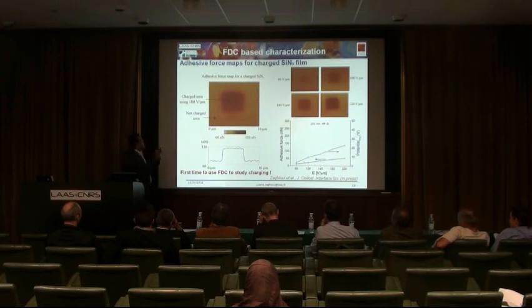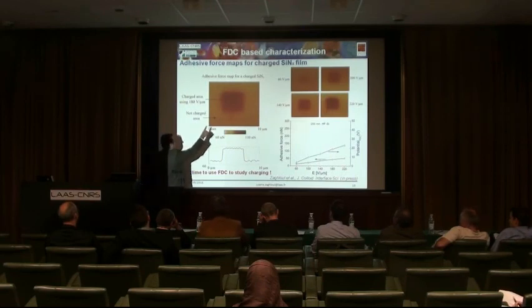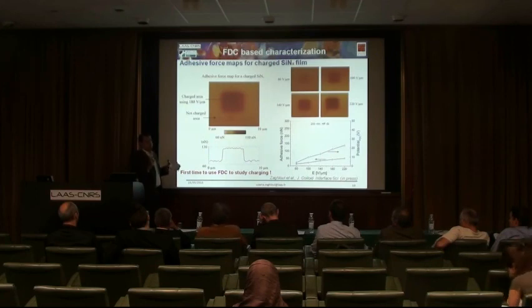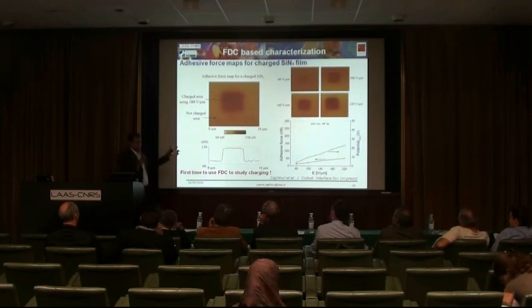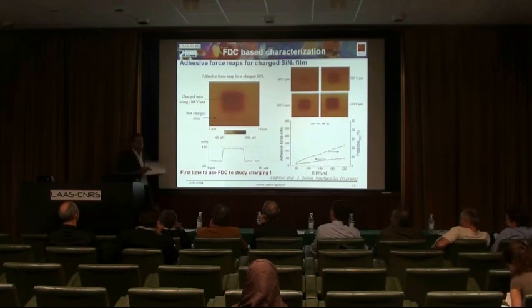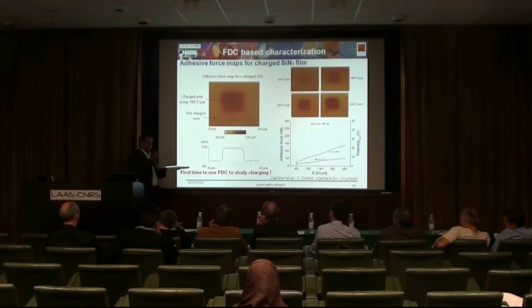The first thing is we can charge in two different ways. The first way is just to go with the AFM tip and scan it line by line. With this, you can control the contact force during charging, because the AFM tip is in contact mode. So you come and you touch the surface. Before touching the surface, there is a parameter you define called the deflection set point, where you're asking the system to have a specific contact force between your tip and the surface. So I might touch it like this or like this.